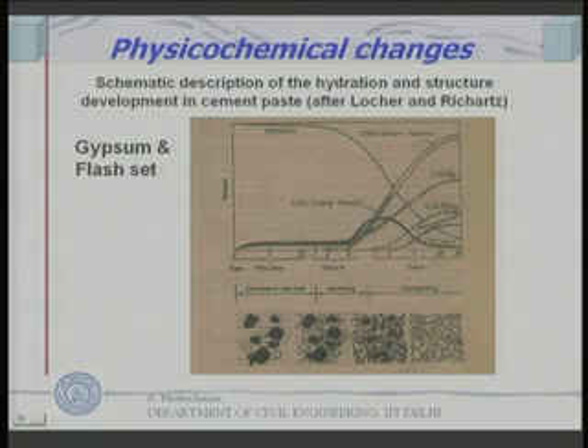Okay, the details of the mechanism at the moment we are not interested in, but we understand that initially the gypsum will react with tricalcium aluminate, forming what is known as ettringite, and this ettringite is then converted into monosulfate later on, which you can see: the ettringite concentration reduces, and instead the monosulfate concentration increases. This is the monosulfate concentration. C4AF, which is another minor compound, is not so very important, but its hydration products start forming after about 7 to 8 hours, and so on and so forth.